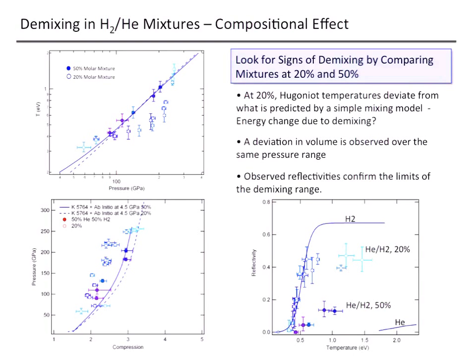We've also looked at 20% mixtures, and we can compare our data, the Hugoniots essentially, to what's predicted by simple linear mixing models. We can see if there's any compositional effect by comparing a 20% versus 50% mixture. What you can see is that the 20% mixtures deviate both in temperature and in volume, essentially P-rho, from what this simple linear mixing model predicts.